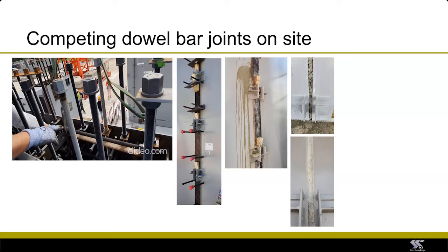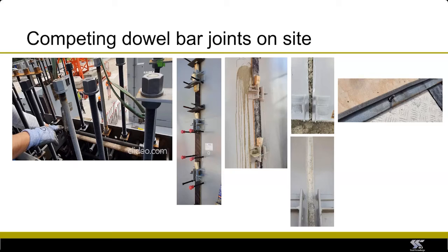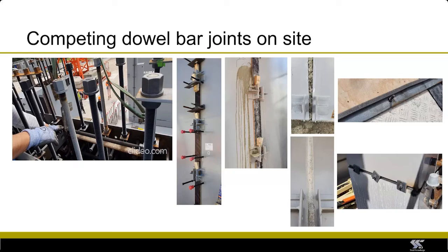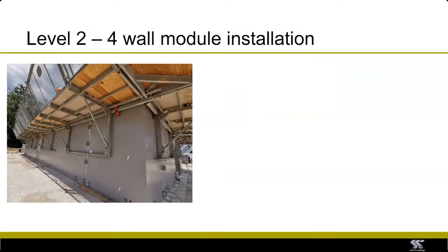But there was clearly a need for a different way of doing this, and so the site team then developed an alternative system, which was a steel plate, a thin steel plate that fitted on the inside of the joint, held in position using short studs and these little square plates. And this worked extremely well because it's on the inside of the joint, so the concrete pressure actually pushes it against the joint and helps to close the joint even further. And this was fine for the remainder of the project.